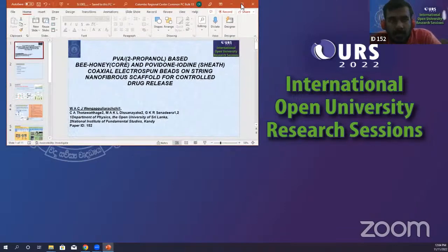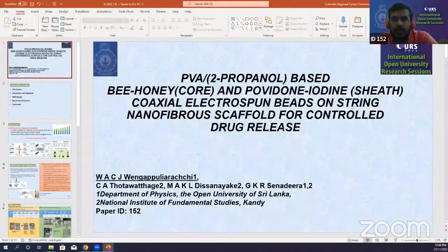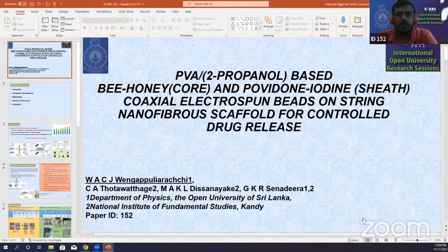So the substrate that you have used is paper or something like that? Generally, for trial and testing, we used just aluminum foil. But after further testing, we used a tea bag simultaneously with aluminum foil, attached to the collector drum, so that we can do the electrospinning with much ease. There won't be any issue if we use a thin tea bag. So we can use this tea bag as a physical attachment to the wound instead of using gauze or anything else.